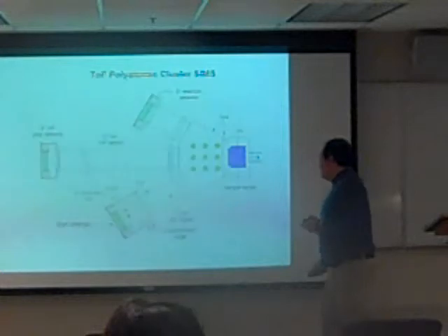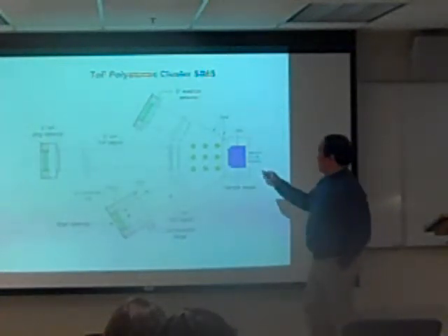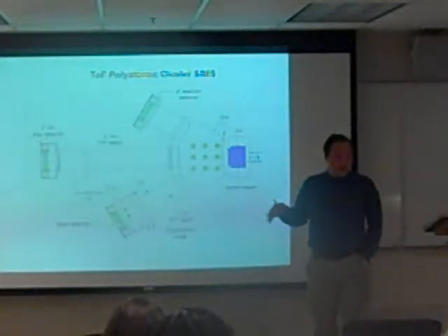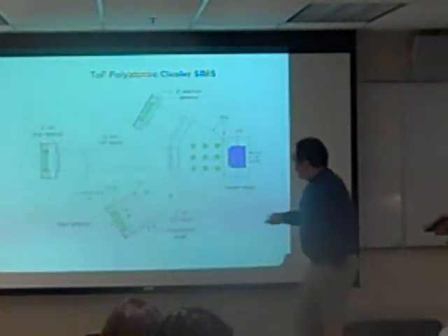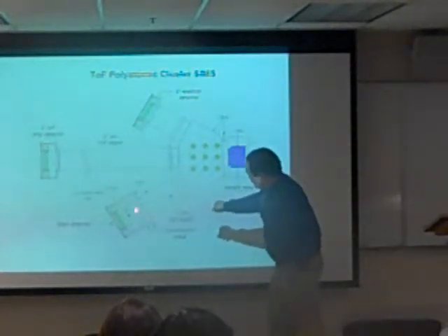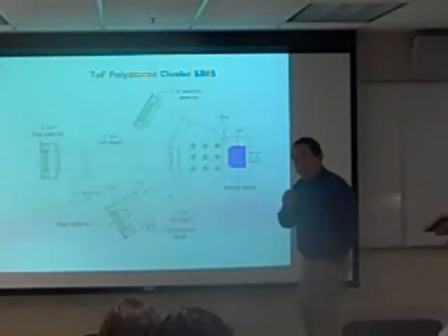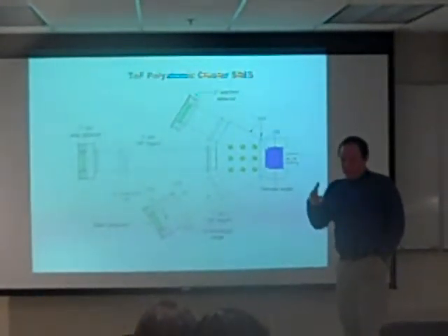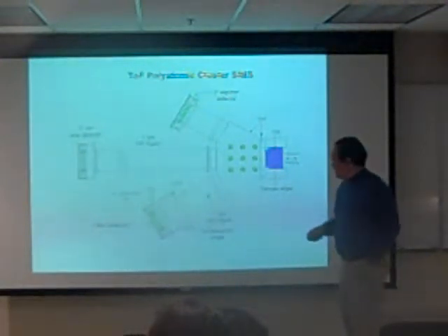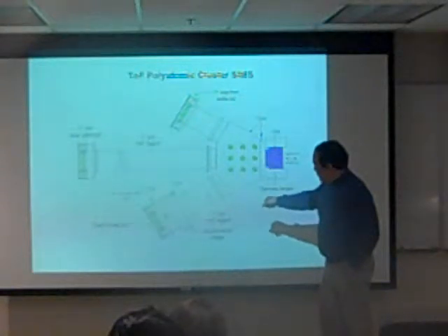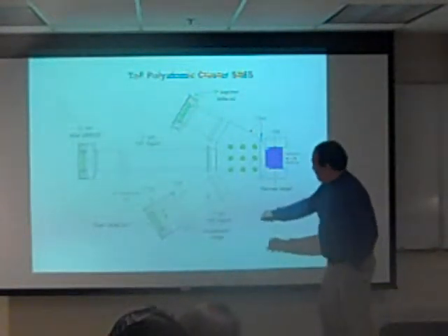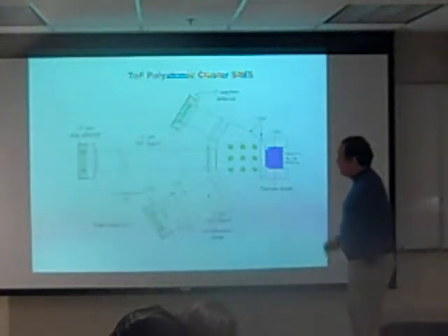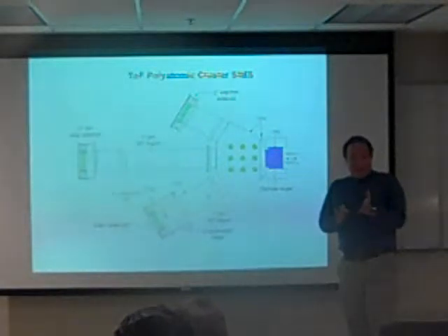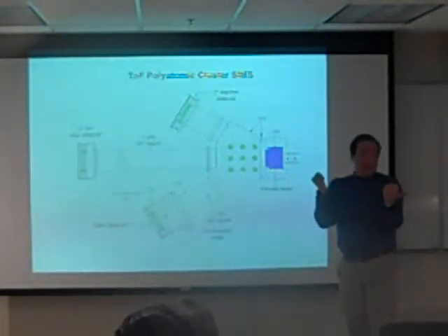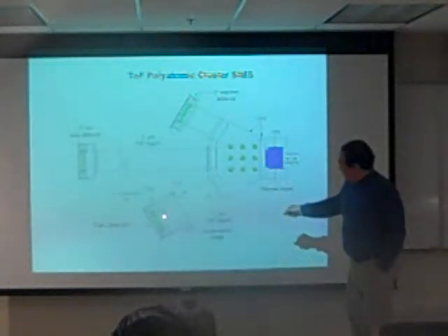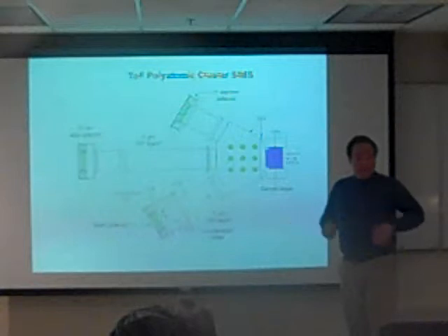We were able to do this with a home-built setup at Dr. Emil Schweikert's lab over at Texas A&M. I borrowed his machine. This setup has a mylar foil that can be coated with different cesium iodide projectiles, just painted on. You could put in buckyballs, you could put in different cesium iodide clusters right there. This is a californium radioactive source, and one thing that's very interesting about californium is that when it radioactively decays, it emits fission fragments 180 degrees opposite of each other. So when a fission fragment hits this spark detector and hits this mylar foil, it hits it simultaneously.